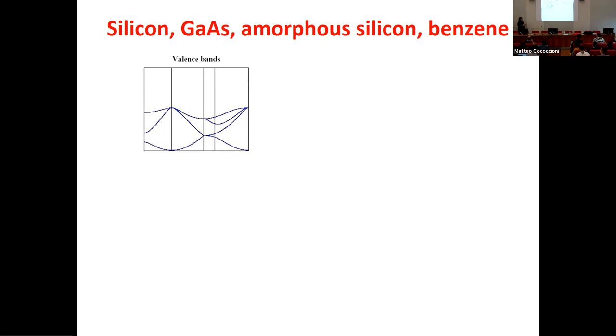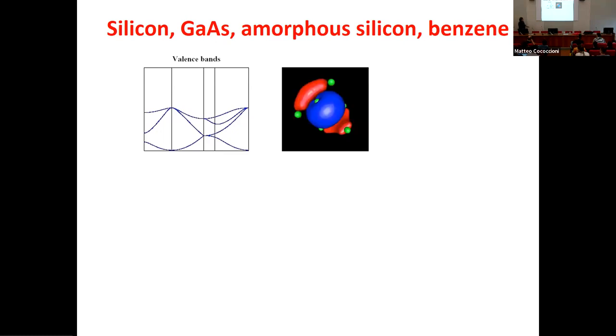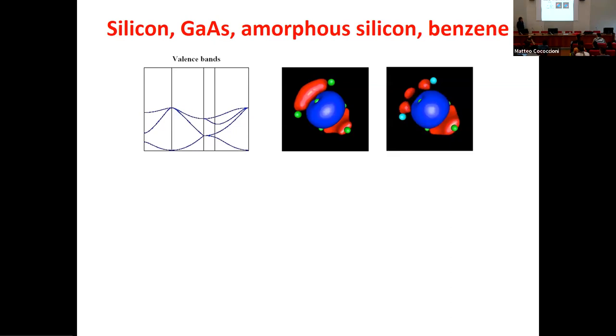And then we ask the Wannier code to minimize the functional omega by doing gradients, taking a finite step, then gradient again, finite step, gradient again. And so we create a sequence of small unitary transformations until we can transform, in this case, four silicon bands into four Wannier functions that, for silicon, look very satisfactory as a representation of the chemical bonds.